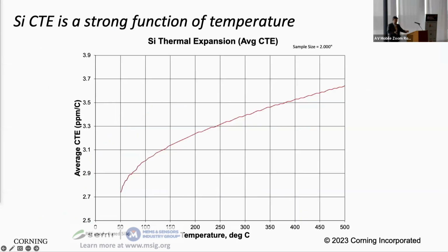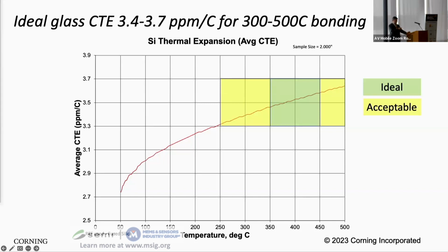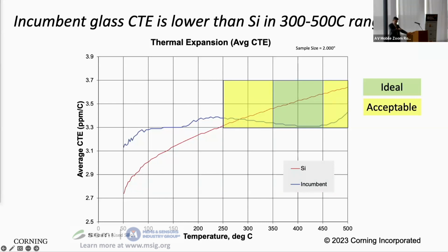And silicon's CTE is a function of temperature. There's a strong dependence. And the 2.6 that everybody uses is really only applicable in the room temperature range. If you bond silicon to another material at high temperature, you want the match to happen at the bonding temperature and not at room temperature. So this is silicon, and if we want to bond in the temperature range that I mentioned in the previous slides, you want to be in the green zone ideally, and outside of the green zone, the yellow zone is still okay for bonding, but you may suffer either throughput or quality issues. And so we want a glass that matches the average CTE in the green zone. The incumbent glass actually works pretty well in the low temperature range, but if you bond it at the ideal 350 to 450 temperature range, it's actually not very well matched. So you would expect some bow after you bond it and then cool down to room temperature.